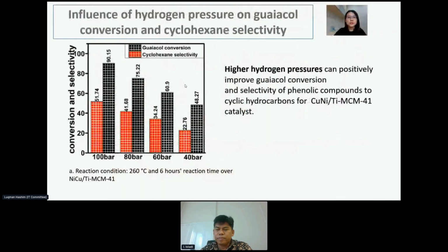The effect of reaction pressure on the guaiacol conversion and the cyclohexane selectivity was further investigated by using the copper-nickel supported titanium MCM41 catalyst. Based on the results, it indicates that higher hydrogen pressure can positively improve the guaiacol conversion and also enhance the product selectivity of these phenolic compounds into cyclohexane, which is a cyclic hydrocarbon compound.